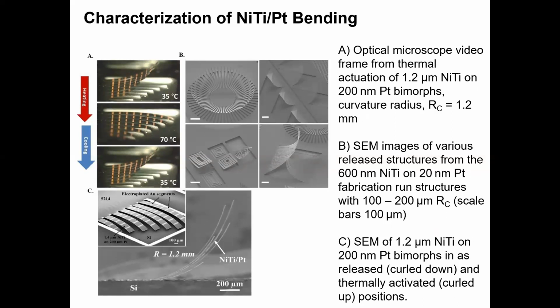Figure B shows the case where the NiTi and platinum layers were both thinned down. In this case, 600 nanometers of NiTi, which was half the original 1.2 microns in figure A, and then 20 nanometers of platinum, which was 10 times thinner than the original platinum thickness of 200. So the thickness reductions here allowed for a curvature radius of about 150 microns, which was a reduction close to a full order of magnitude from the 1.2 millimeters in the thicker stack. So the main takeaway here, I would say, is that the NiTi and platinum thickness ratio strongly influences the curvature radius. But in both cases, a significant two-way shape memory effect was achieved using thermal cycling.